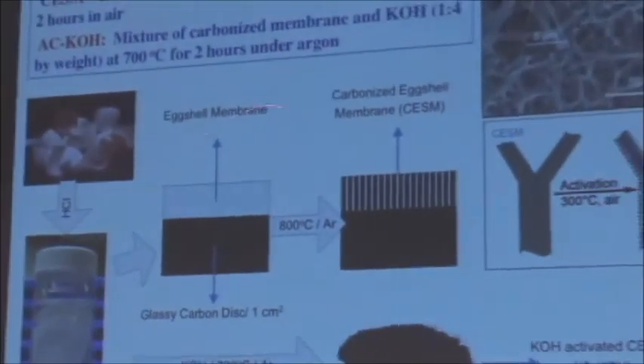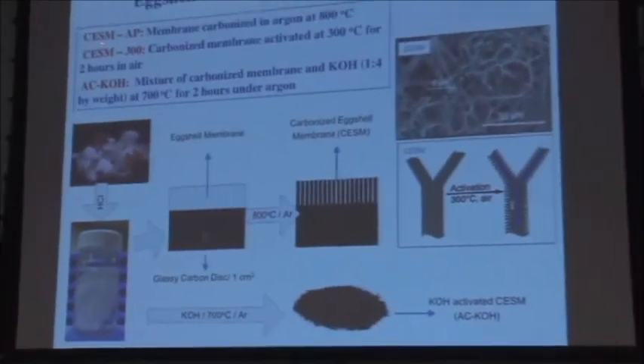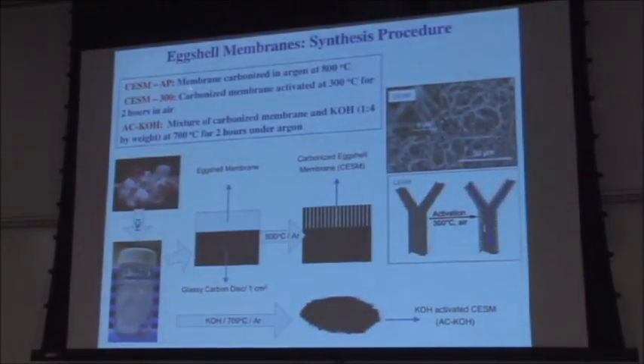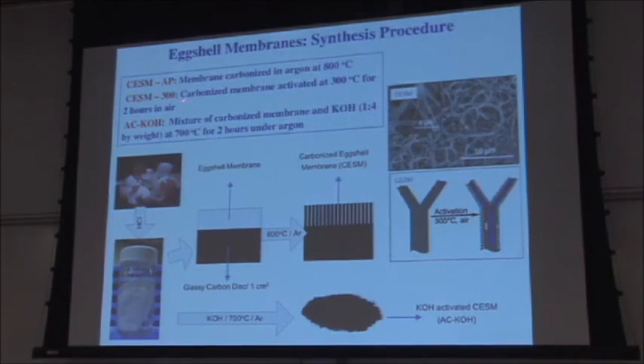So we took this eggshell, removed the shell, have the membrane. We carbonized the membrane. And those CESM-AP, so carbonized eggshell membrane, as prepared. Basically, the membrane was carbonized in argon at 800 degrees C, so not too much porosity, basically low surface area material. We then took this membrane and just activated it in air for 2 hours at 300 degrees C.